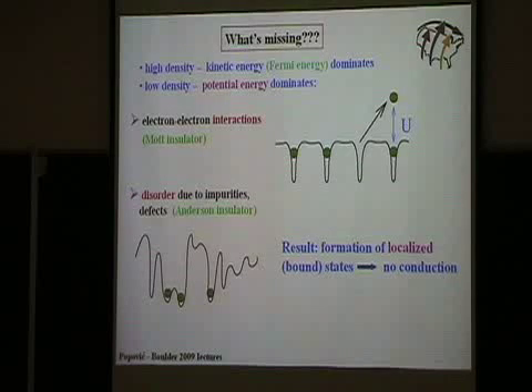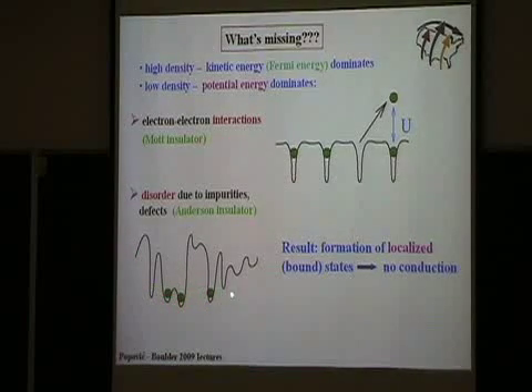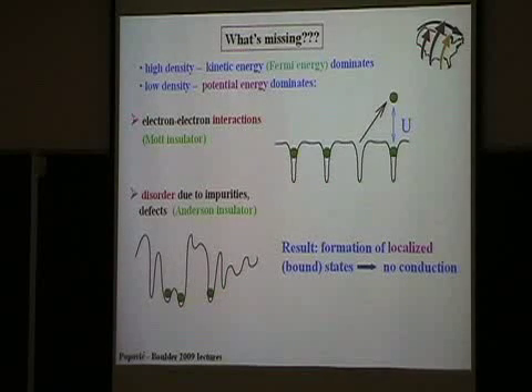Why does it fail? It ignores two important effects. We have a low concentration of carriers, so in this case the potential energy becomes dominant, and when we have very strong Coulomb repulsion between the electrons, this will tend to localize the electrons because they repel each other. They want to be as far as possible from each other. Also, in any real material, there is disorder due to the presence of impurities, defects, and so on. So there is always some kind of random potential. At low densities, the electrons will localize in these potential wells. They will get stuck. Both of these effects lead to the formation of localized states, so that even though we do have carriers, there is no conduction at zero temperature because they're localized.